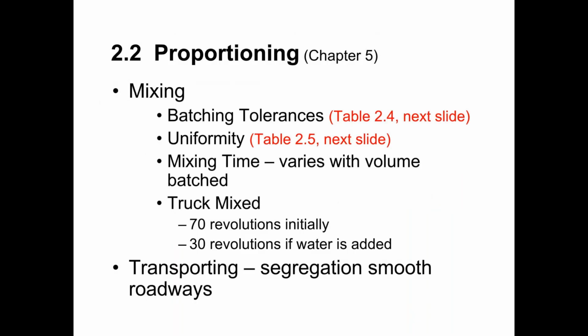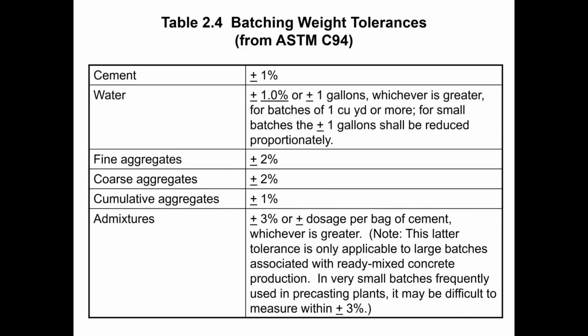So that's the batching process. Now let's talk a little bit about mixing. So batching tolerances are given in table 2.4 on page 215. And so for our cement, the tolerance on batching of cement is plus or minus 1%. For water in your book, it says plus or minus 1.5%. That's a typo. It should be 1.0%. Or for smaller batches, we may switch over and use the plus or minus 1 gallon. But generally in precast plants, we're batching sufficient volume that the tolerance on water is plus or minus 1%.